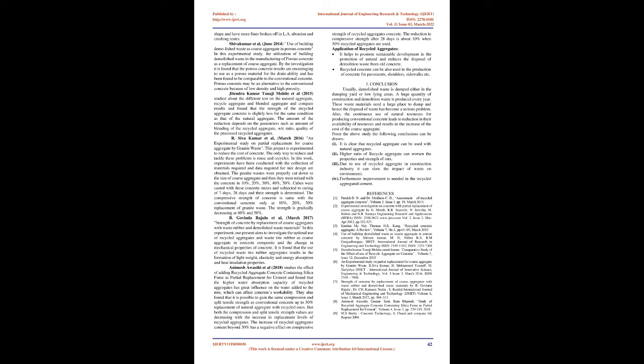R. Shivakumar et al., March 2016, an experimental study on partial replacement for coarse aggregate by granite waste. This project is experimented to reduce the cost of concrete. The only way to reduce and tackle these problems is reuse and recycling. In this work, experiments have been conducted with the collection of materials required and data required for mix design are obtained. The granite wastes were properly cut down to the size of coarse aggregate and then they were mixed with the concrete in 10%, 20%, 30%, 40%, 50%.